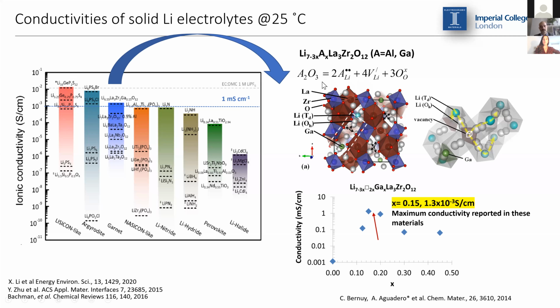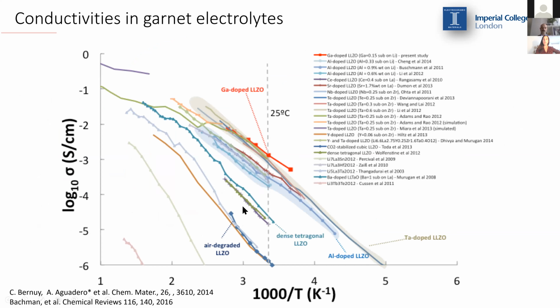We have achieved this by controlling the concentration of lithium vacancies and interstitials in a network of tetrahedra and octahedra that are sharing faces, so achieving a very high conductivity with low activation energy. This is achieved for a composition of 0.15 gallium per formula unit, as will be described later also by Federico. Here it is just showing how this particular composition has reached the maximum conductivity within the garnet substrate.